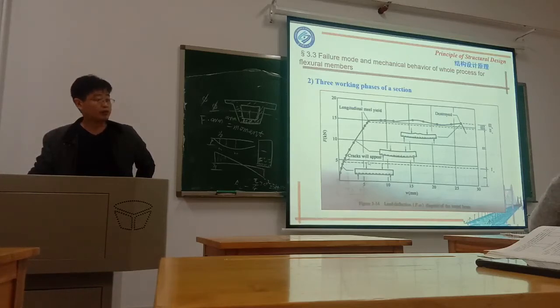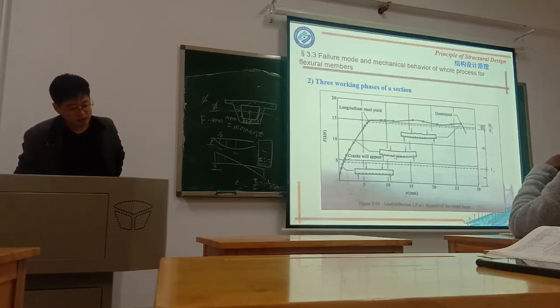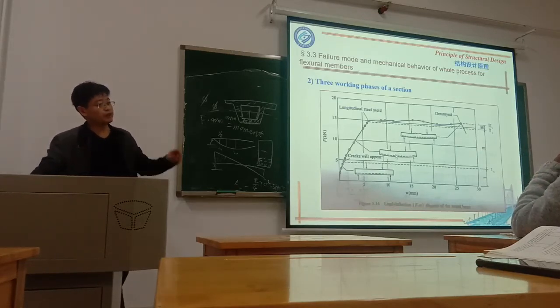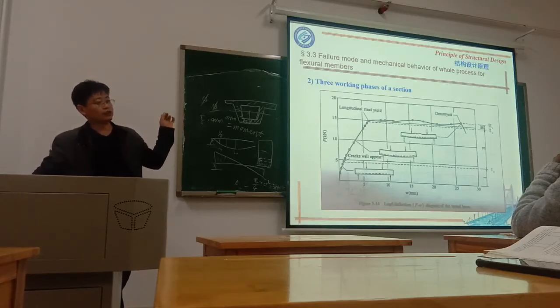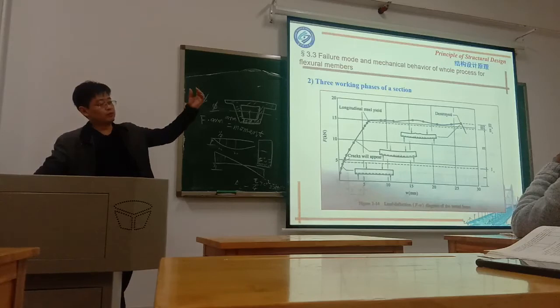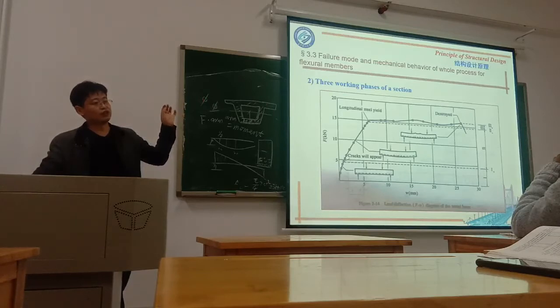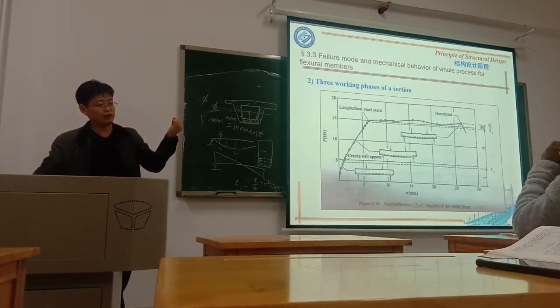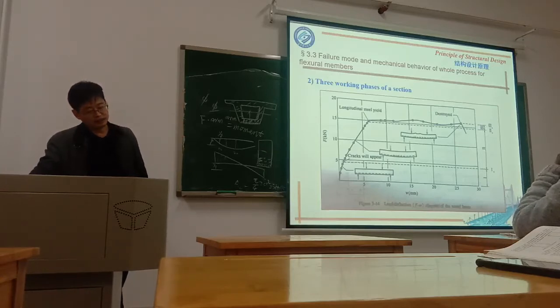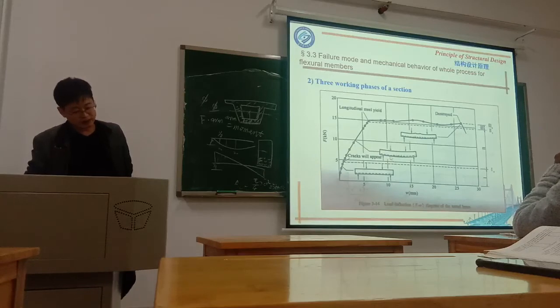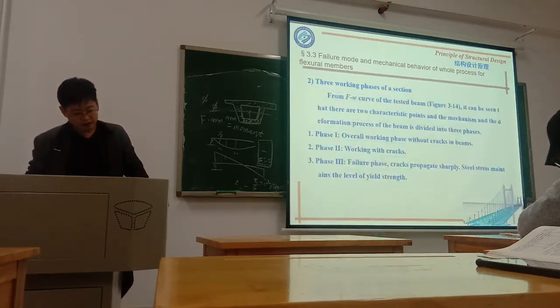But at the end of this part, when we get into the second part, cracks will generally appear. With the load increase, the cracks will increase greatly. At this position, you should know that once the crack appears, we use the assumption that the concrete no longer resists the tensile force. All the tensile force is transferred to the steel bar. That means at this position there is a redistribution of the tensile stress, so we see this distribution in the figure.